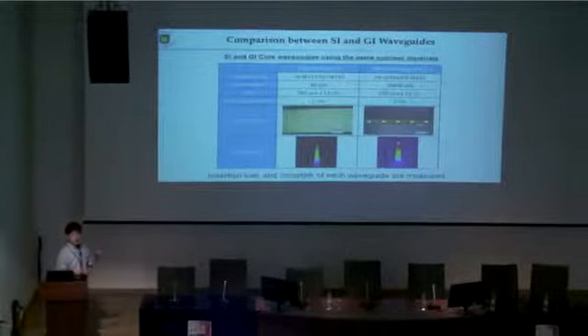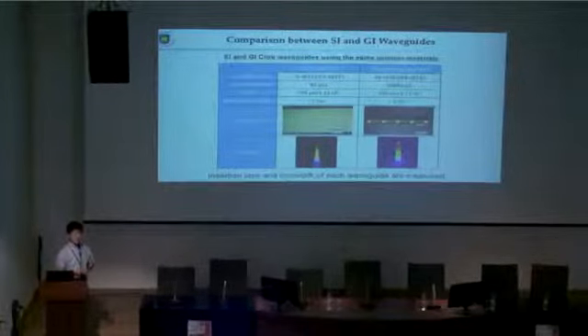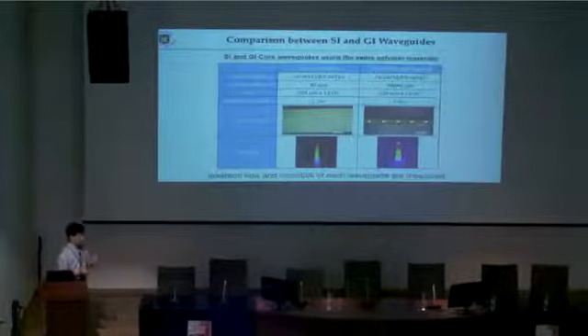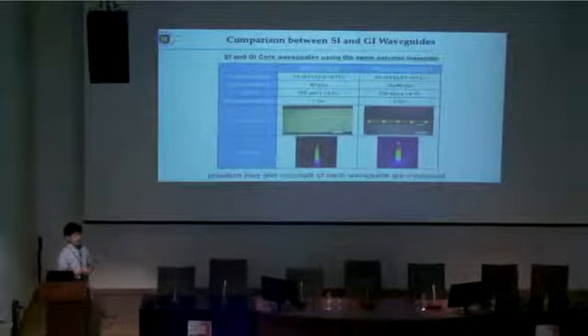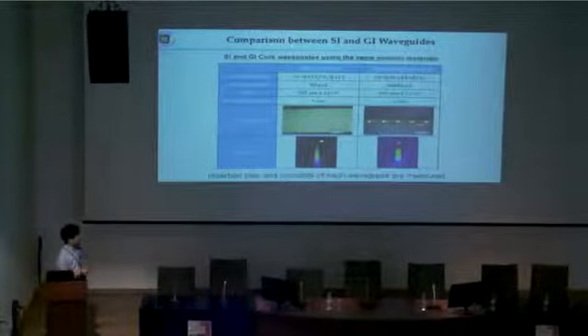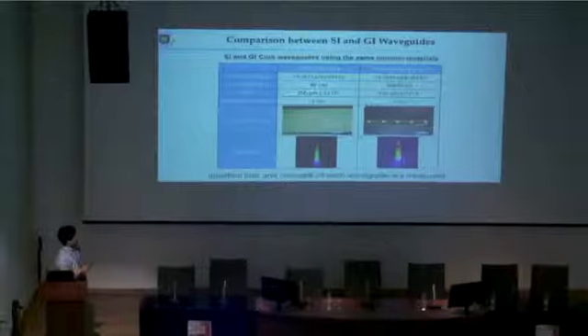And then we are evaluating optical characteristics and comparing to the existing step index square core. So far, we could not have the step index and graded index waveguide composed from the same material. Therefore, we haven't evaluated a fair comparison between the SI core and the GI core. However, with this siloxane-based material available from ADEKA Corporation, Japan, not only a graded index core, but also a step index square core waveguide is fabricated successfully. This is fabricated by ADEKA Corporation, not by us. So now the core size is the same, the pitch is the same, and the length is the same.